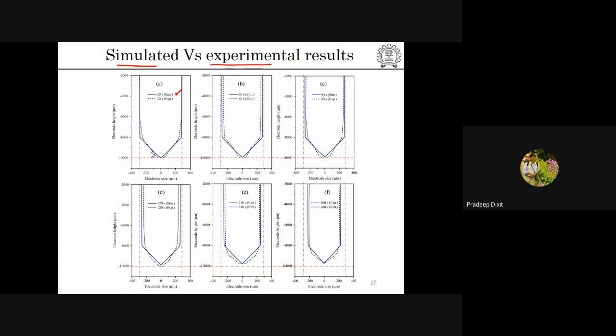For our case, it was very difficult to find out the current efficiency. We have no idea of the current efficiency, so we took a value from the literature, for example 95%. But it appears that this value was not really correct, and because of that we were getting some difference between simulation and experimental results. After a lot of optimization work, we were able to get this kind of a feature. So here are the results.